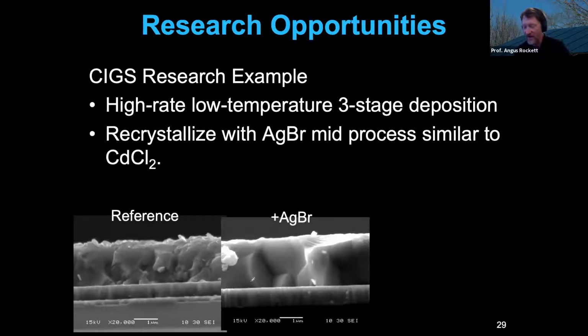One of the ways that devices are made, although not how Solar Frontier makes theirs, is a so-called three-stage deposition process. So what we've done is we've increased our deposition rate by a factor of 10, turned down our temperature by 200 degrees C. We get pretty lousy material, and it's shown here in this SEM image. And what we've shown is that if we interrupt that deposition process with just a few minutes of deposition of silver bromide, look at how much better this crystal structure is in this bottom material. We have huge grains in the material compared to little tiny grains in the reference material. It makes a much better solar cell.